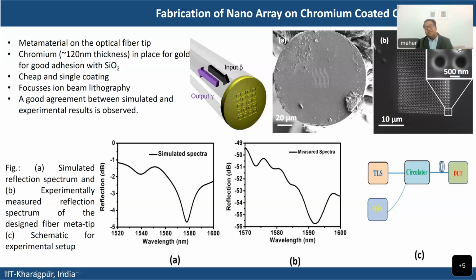And the material which we used is not gold here; it is basically chromium. And why did we not use gold? Because gold sticks very loosely on silicon dioxide, and we know that optical fibers are made of silicon dioxide. So for good adhesion, we use chromium basically.